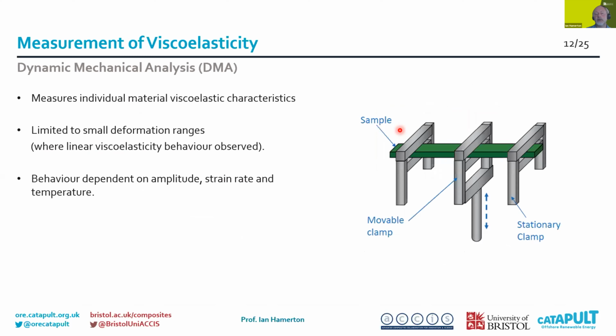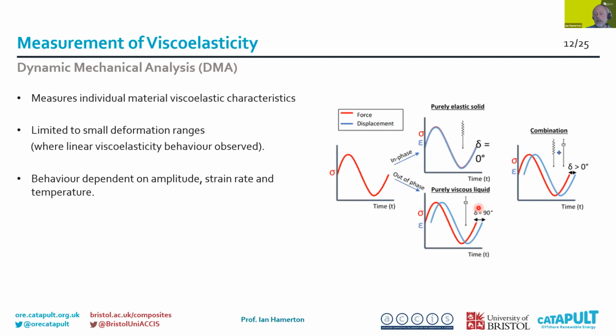So the move with viscoelastic materials has been to shift towards the use of dynamic mechanical analysis. And this is a simple structure here where a beam of the material, be it composite or coating material, the polymer, is held in secure clamps and then is vibrated using a sinusoidal force from this movable clamp in the center. That produces essentially a plot of either the force or the displacement.